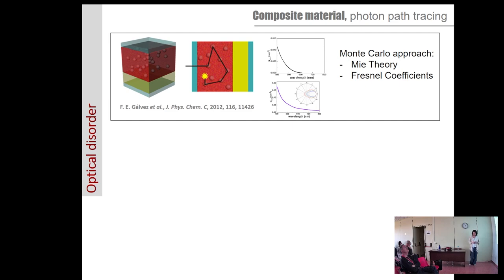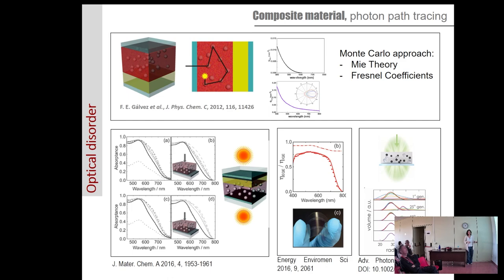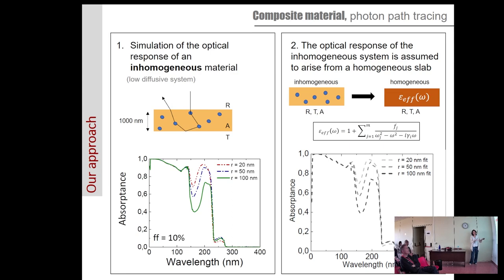So we said, okay, we have a way to describe the optical properties of an inhomogeneous system, where we have an approach where we combine Monte Carlo, Mie scattering theory and Fresnel coefficients. So basically, we send a lot of photons to our system, follow them, and then we can have the absorption of all materials inside the system, the diffused components, and so on and so forth. This is something that we have extensively used for solar cells here, bifacial or flexible, but very recently also to extract the internal nanostructure of a porous TiO2 film, for instance, by combining this with a genetic algorithm and so on. But I'm not going to give the details here, but it is employed.